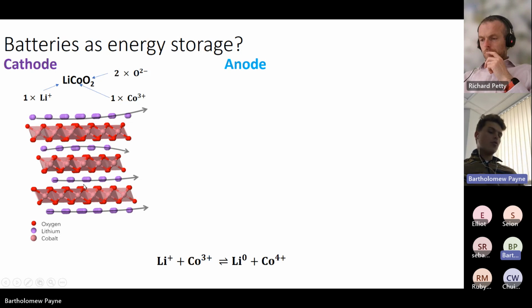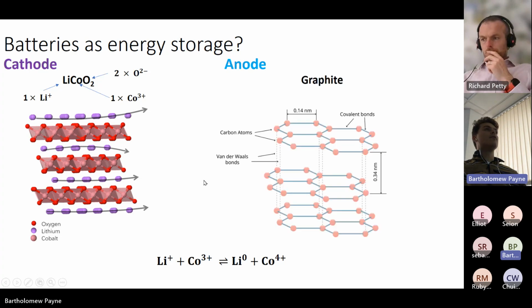So now you've got your one redox reaction happening on one side, where your cobalt is going from 3+ to 4+. So at the anode, we must somehow do something with the lithium to change it there. And what we have is graphite. It sounds stupid, your regular old graphite, where each carbon is bonded to 3 carbons within its own layer, and then there's a larger gap or separation between each layer. But what we can do here is exactly the reverse of what we've done here, and we can actually stabilize lithium somewhat in between these layers of graphite, or graphene sheets.